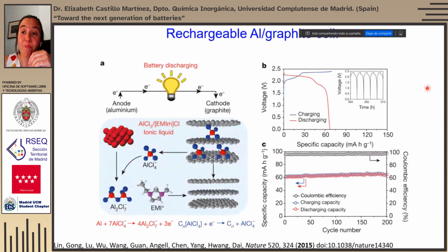The final multivalent chemistry will be that of aluminum batteries. Aluminum exchanges 3 electrons when it is electrodeposited or dissolved, but it will have even more problems than calcium or magnesium to be intercalated into graphite. So the strategy is to use electrolytes in which the aluminum ion gets coordinated by chloride anions, and actually what is intercalated is a single charge anion, the aluminum tetrachloride, that can be intercalated and deintercalated relatively easily. So it is possible to achieve reversible cycling during 200 cycles and even more, during thousands of cycles, of this aluminum graphite battery.